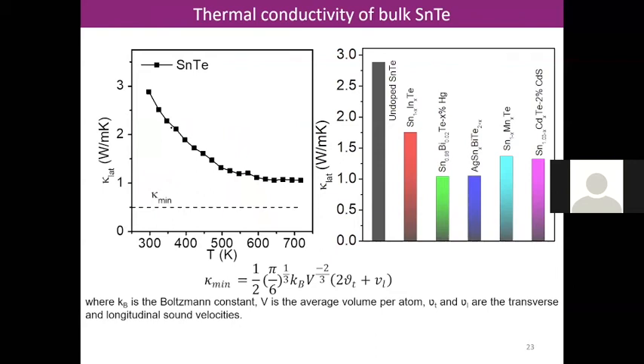So this is the pristine tin telluride thermal conductivity, starting from 2.9 or 3 watt per meter Kelvin and going down to 1.1, 1.2 watt per meter Kelvin. One can calculate the theoretical minimum of the thermal conductivity, the kappa minima, once we have information about sound velocity, because sound velocity directly relates to the acoustic phonon, which carries the heat in a material, as I told you. The theoretical minimum thermal conductivity is around 0.5. So can we decrease from here to here? That was the challenge when we started working on thermal conductivity in tin telluride back in 2014-15.